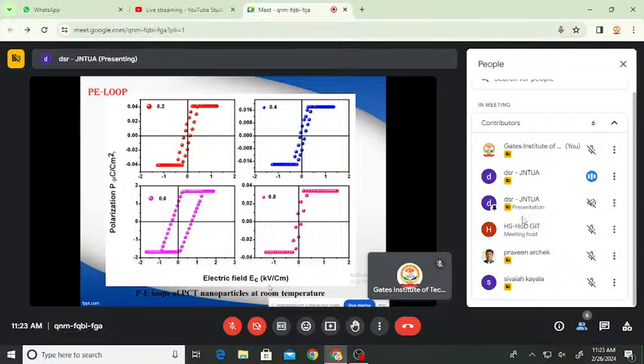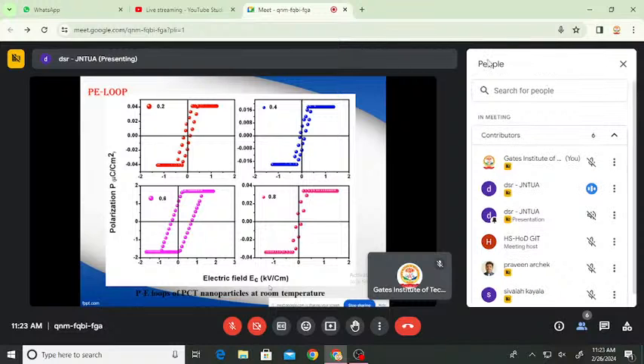These observations were recorded after connecting the pellet parallel to 4 microfarad capacitors in order to compensate the PE loop tracer. So it is seen that all the prepared nanoparticles exhibited explicit hysteresis loop, and the explicit hysteresis loop distorted into banana shape at room temperature. This in turn induces the leakage current that may be ascribed to oxygen vacancies on the top surface of the grains in spite of polarization.